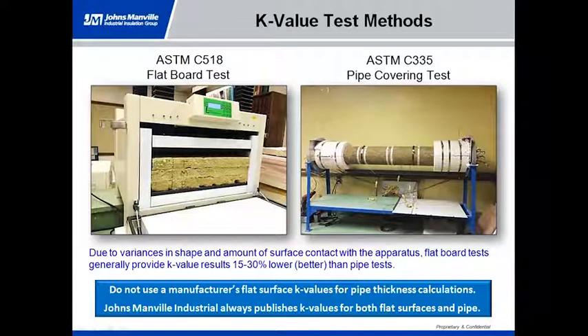We simply have a hot plate, which in this apparatus on the left would be either the top or the bottom. You'd have a cold plate, which would be on the opposite side of the hot plate, and you simply measure how much energy you have to put into the hot plate to keep everything at equilibrium. As an example, for most building insulation, the hot plate would be at 100 degrees and the lower plate would be at 50 degrees for a mean temperature of 75, and you would only apply enough heat to maintain all those temperatures, and from that you can determine what that K value is.